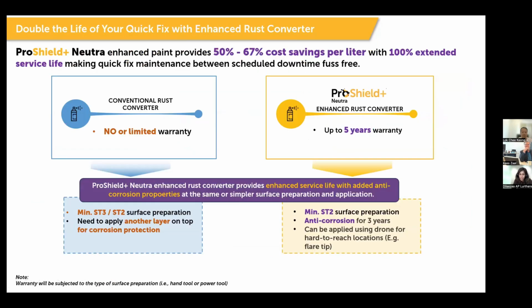And our most recent release is what we call the rust converter, a variation of ProShield Plus. It's otherwise termed as Neutra. This is our rust converter and it's designed for a quick fix. Typically, if you look at a conventional rust converter today, you would have a quick fix solution that has either zero warranty or limited warranty, and it would require a minimum ST3 or ST2 surface preparation. And you would definitely need to apply another layer on top for corrosion protection.